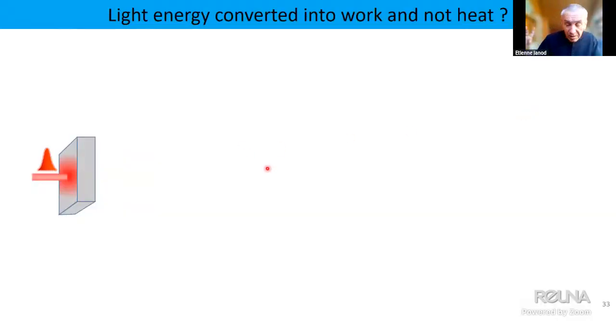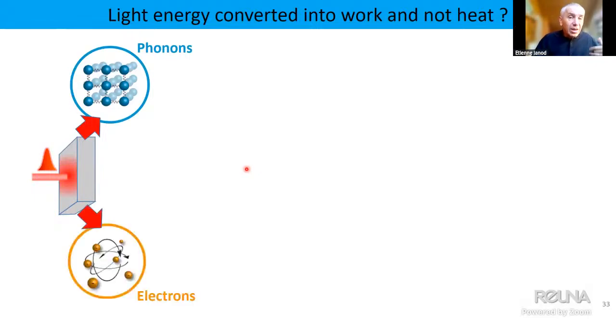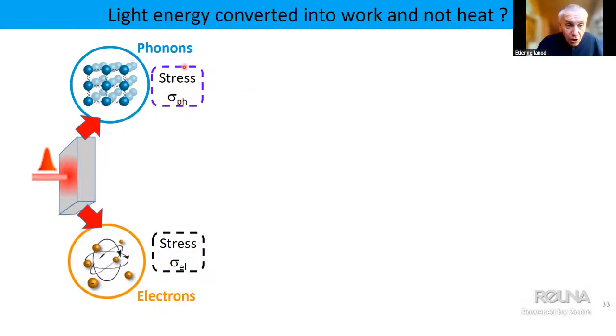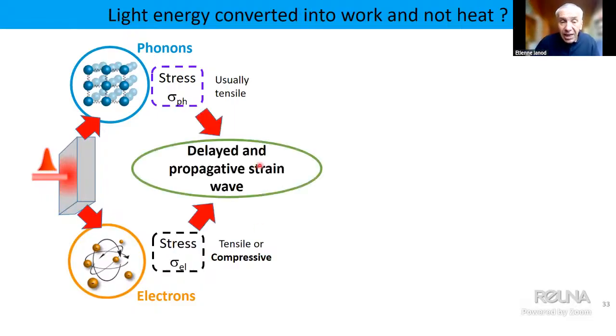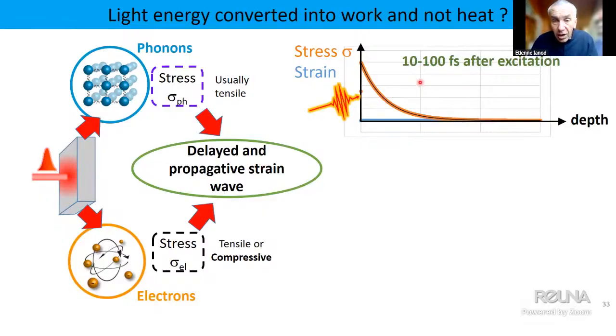Now I will just recall something a bit more theoretical. When we send the laser to a material, what is quite well known is that the energy can be transferred into electrons and stay in the electron channel, especially in insulators. If you are in a metal, rapidly the energy of the electrons will be transferred into phonons, meaning it will generate incoherent phonons. By doing so, you generate some kind of mechanical stress that for the phonon part is usually tensile, but for the electronic part can be tensile or compressive. And this mechanical stress is relaxed by the propagation of a strain wave that starts from the surface of the material. Here, I explain what I just said.